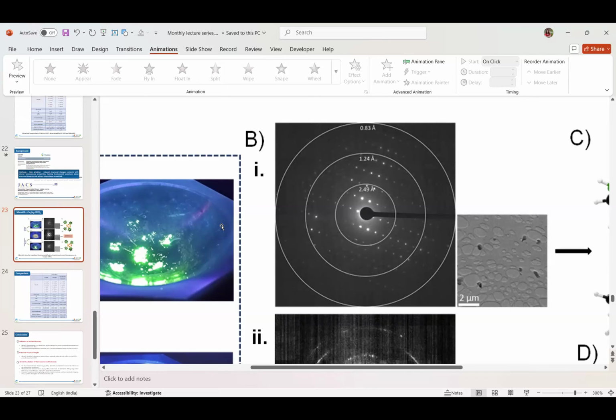I really enjoyed her presentation as usual. She has been very dynamic, and there are certain questions about certain details here because we are not really doing these, so it is more important to know about them. Of course, this points to several questions such as orientational disorder. What can you do about this orientation? How can you stop this orientational disorder? Now, you are doing this experiment at 77 Kelvin. Does it mean that you need to cool down even further? What kind of rotational disorder is seen in carboranes? At what point does carborane rotation stop? For example, methane will keep rotating even at 20 Kelvin, so you need to go down to 10 Kelvin to stop rotation. But I don't expect carborane to be rotating at so low a temperature.